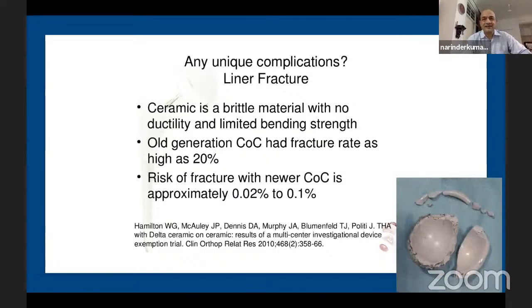But there are unique complications with ceramics. Because ceramic is a brittle material, thin liners can fracture, especially during insertion, as taper junctions are still a challenge - Martin will probably tell us about that challenge with the liners. The old first and second generation ceramic-on-ceramics had a fracture rate as high as 20%, which led to them falling into disrepute. But with Delta ceramic, the fracture rate has come down to less than 0.1%, which is absolutely acceptable.